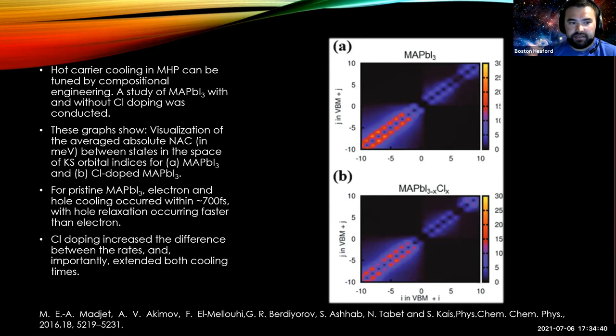And for the pristine system, the electron and hole cooling occurred within about 700 femtoseconds, with hole relaxation occurring faster than the electron relaxation. In the chlorine doped system, it increased the difference between the hole and the electron cooling rates, but importantly extended both cooling times. So chlorine doping extended the hot carrier lifetimes in the system, which is again good.